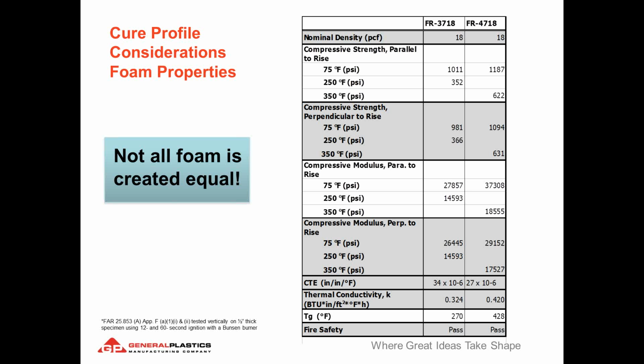Other test methods will report it from minus 20 F to plus 20 F. Now that's not very useful for most tooling operations, and also depending on the type of filler used in the material can give you an artificially low CTE. Now when you heat these materials up, the test method is basically the substrate is saturated at that temperature. So what that means is as you're looking at the CTE value of 27 ppm, that 27 times 10 to the minus 6, that value is of the foam saturated over that temperature range. And we'll come back to that point in a minute because there are some correction factors that you need to use to get an effective CTE. And also, most of the foams that we make that are FR prefixed do pass fire safety, which is basically they will not support combustion once a flame has been removed.